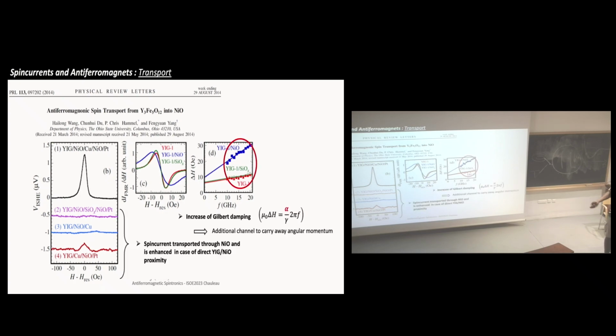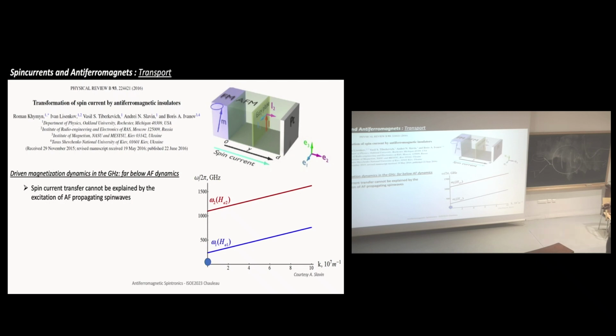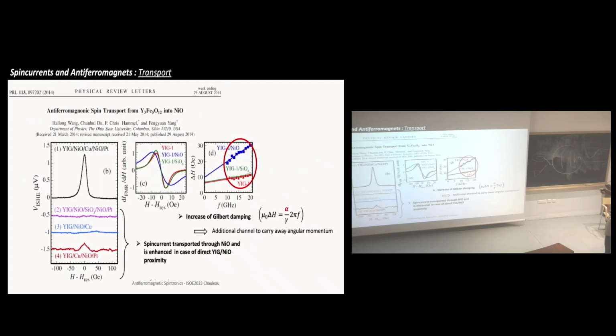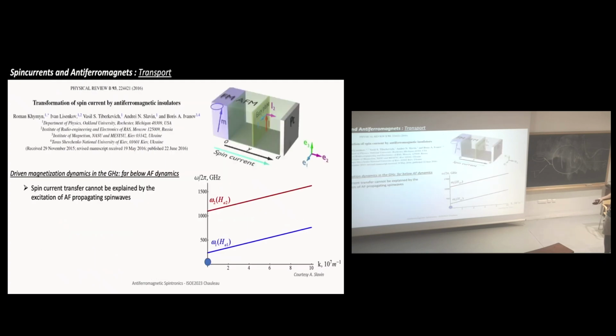Okay, so that was two very important studies for the beginning of antiferromagnetic spintronics with oxides. That was at the very beginning, and I will come back to your talk just a bit later. Soon after, they asked, how come we managed to see something, because we are so far from the resonance frequency of NiO? I've just told you that the resonance frequency of NiO was at 1 terahertz, with another mode at around 170 gigahertz, and here they excited at a couple of gigahertz. So they are very far from the resonance frequency.